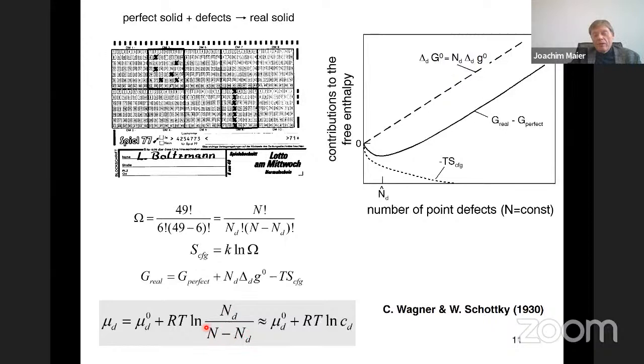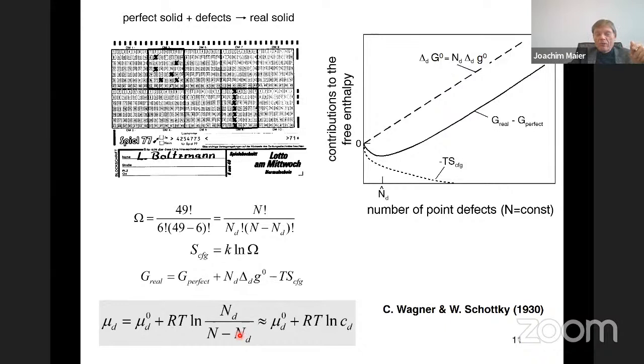If dilute, you get the Boltzmann form, well known for at least 100 years. More precisely, the expression also involves the number of free sites, which changes as more defects form — this is Fermi-Dirac type statistics. This kind of statistics applies because you can occupy one site only once; the Fermi-Dirac distribution does not necessarily have to do with quantum mechanics — it's analogous to the Langmuir isotherm.